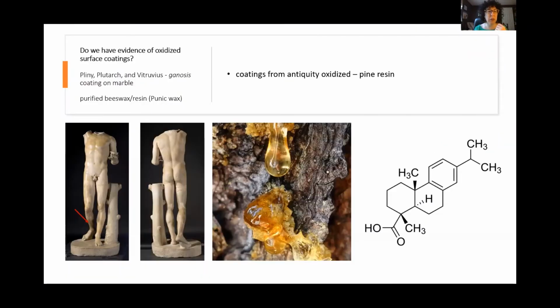But then we wanted to see if we really think that these stains are due to organic surface coatings, can we find organic surface coatings elsewhere on the sculpture? And in fact, we could, and we would expect that. If we look at the writing of, for example, Pliny or Plutarch or Vitruvius, they all talk about the process of ganosis, the coating of marble with Punic wax, which would have been a mixture of purified beeswax and plant resin.